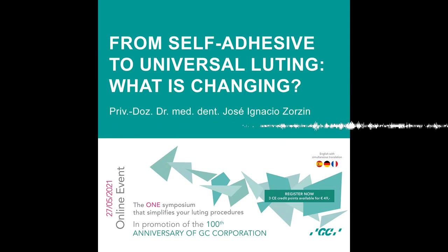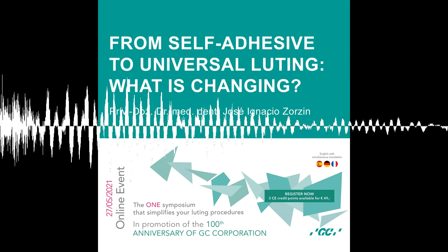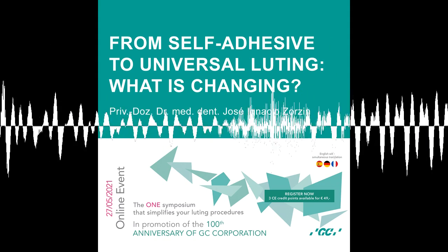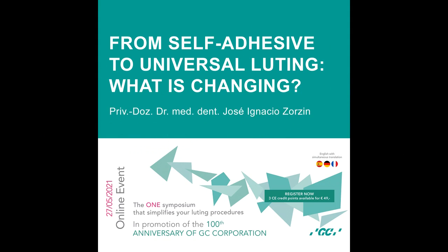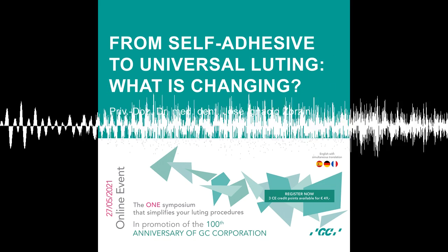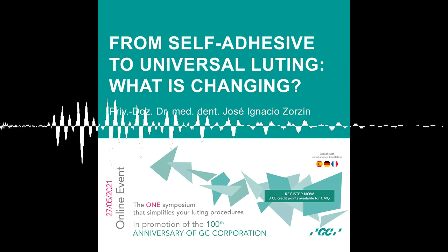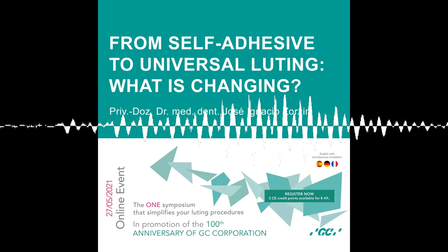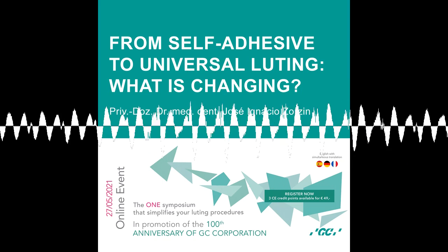Yeah. Makes sense. But the most interesting question, even when it comes to glass ceramic, what do you do after the etching? Do you clean the etched surface? There are some people claiming that there are a lot of precipitates inside after the etching. You can put it, for example, in an ultrasonic bath and clean it. That's a possibility. Others etch it again with phosphoric acid, I heard.